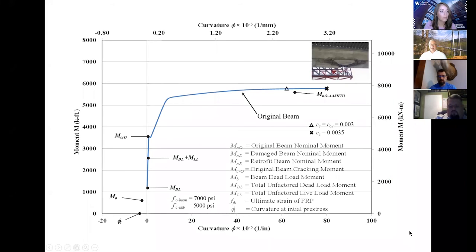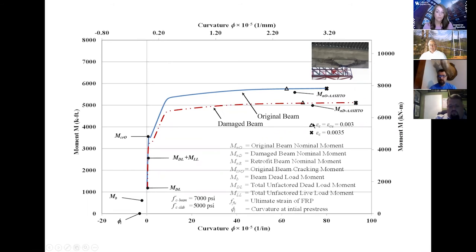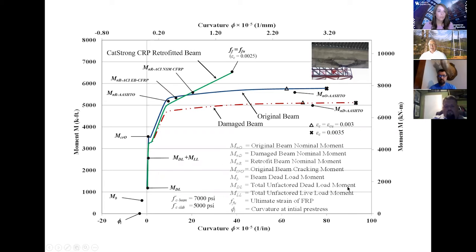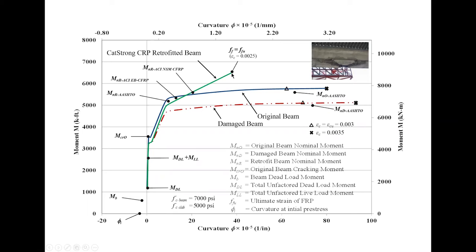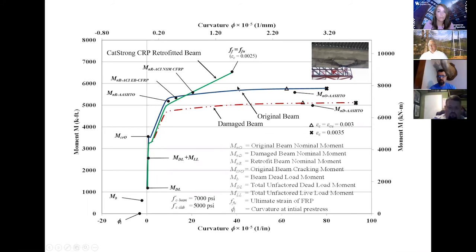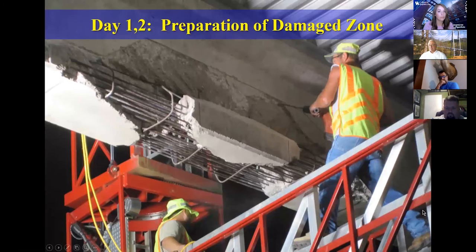The way we do the repair is first, we evaluate the capacity of that beam as it was built originally. And then we evaluate the capacity of the beam when it was impacted. So it's reduced quite a bit in here. And then we evaluate the capacity of this beam when we strengthen it with CatStrong. So it goes quite a bit higher than the original capacity with the CatStrong in there. But of course, with design guides, we put limits on a number of things. So we do all this evaluation, and then we do the design for the repair, and then we oversee the repair.